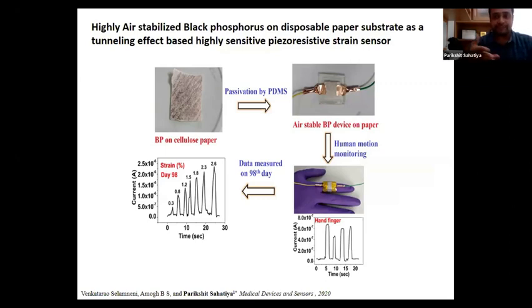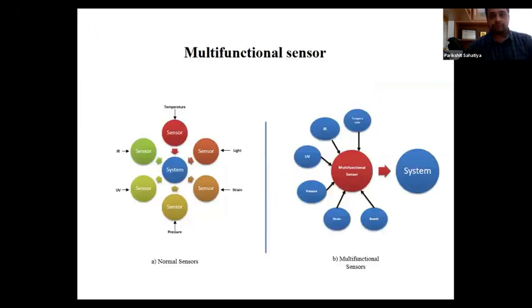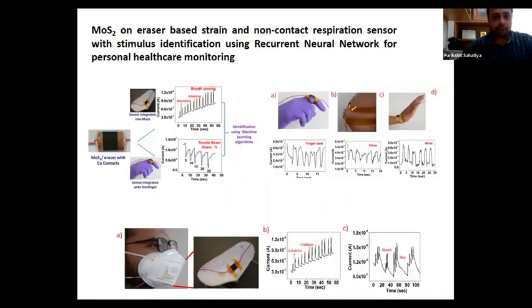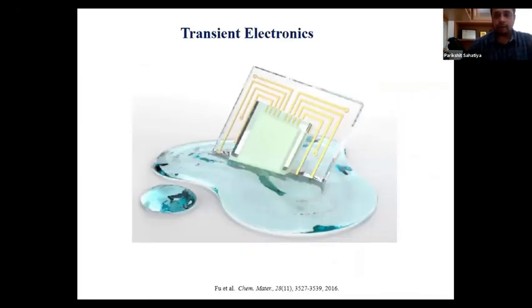The two things that we achieved in this research: first, a black phosphorus based sensor which is stable for 98 days. Because black phosphorus is highly oxidized, it is very difficult to make the device stable for 98 days. That was one thing that we achieved. And also the sensitivity that we achieved was better than the conventional counterparts. I'll skip this part in the interest of time.